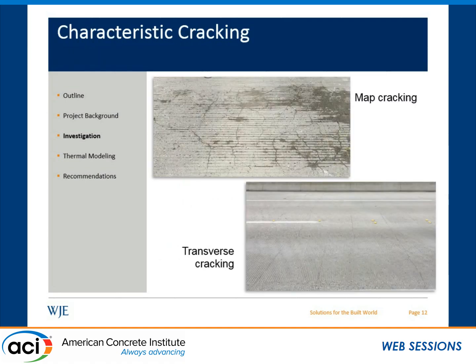So these are some of the characteristic crack patterns that we observed while we were actually out in the field. On the top, you see quite a bit of map cracking, which we noticed on a number of the bridge decks. Our petrographers and subsequent laboratory analysis, we determined that that was mostly due to plastic shrinkage. It was especially pronounced in bridge decks that contained silica fume. Then there's the transverse cracking, which I hope is visible to most of you in the audience on this slide.